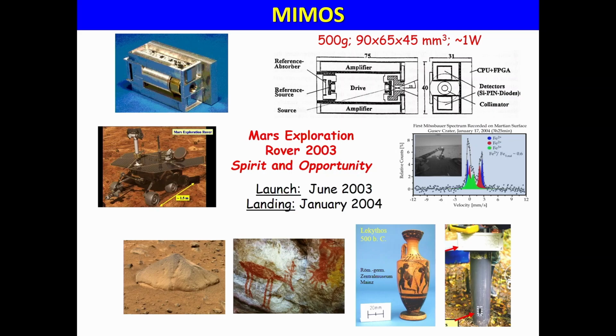So it is exactly the same. If you do some spectrum, you start at a temperature of 77 K, you have no more liquid nitrogen, and one day after you arrive at room temperature, so you have superimposed different states established at different temperatures. So it was necessary to overcome this point. And the second point also was the dust which was on the window.